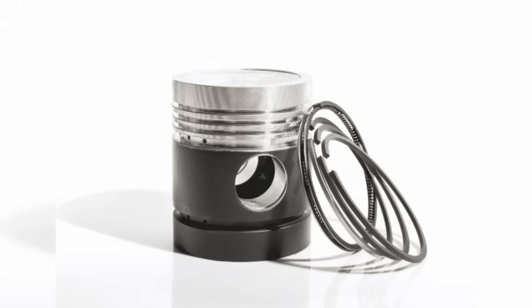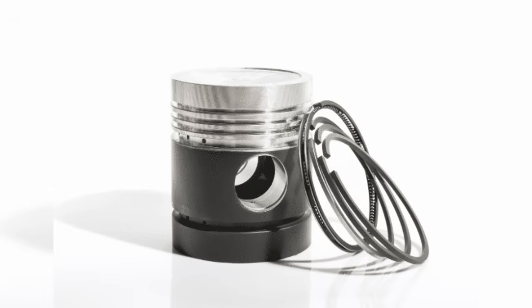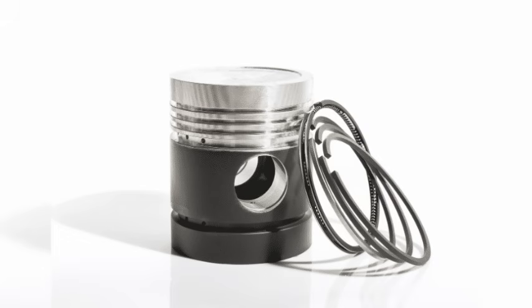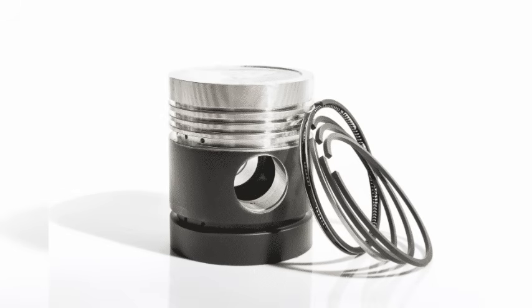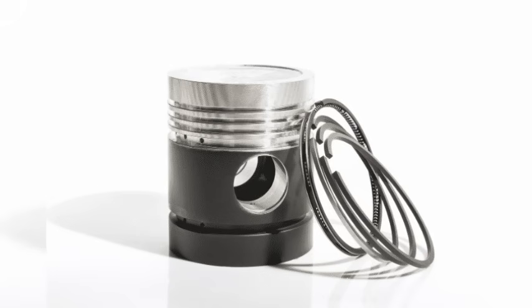The challenges were immediate and substantial. Challenge 1. Plating thickness. Decorative chrome plating was typically 0.0003 to 0.0005 inches thick, a few 10,000ths of an inch. This was enough for appearance, but far too thin for a wear surface. Hastings needed plating thick enough to survive the wear of hundreds of hours of operation. Through testing, they found that approximately 0.004 to 0.006 inches of chrome provided adequate wear resistance, roughly 10 times thicker than decorative plating. This required longer plating time and careful process control to ensure uniform thickness.